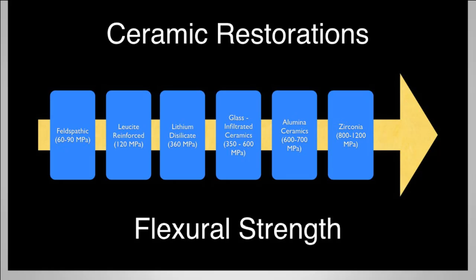In today's presentation, we're going to discuss the two most popular types of ceramic restorations. These are lithium disilicate and zirconia restorations. Lithium disilicate restorations are glass-based and historically exhibit strengths of approximately 360 megapascals. Zirconia restorations do not have any glass, and they have a flexural strength of around 800 to 1200 megapascals.